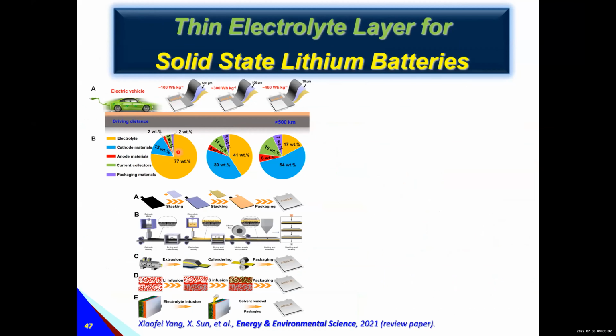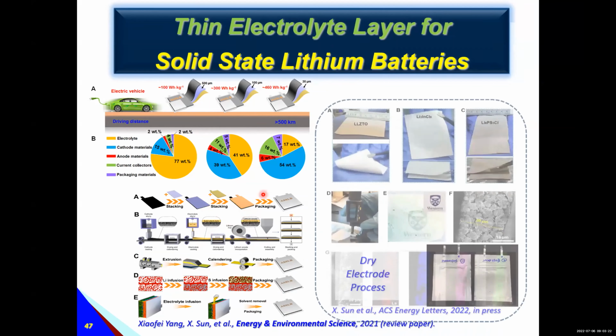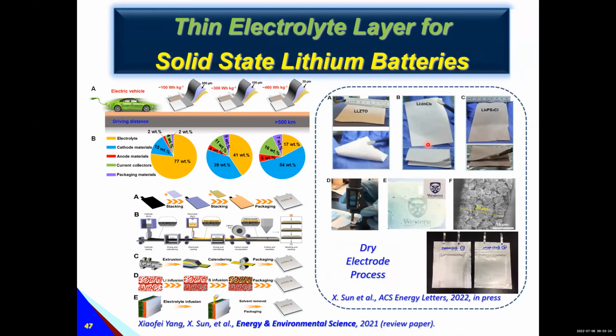Last part, I think not only the solid state electrolyte, we also need to work on the electrode. A very thin solid state electrode is very important for high energy density. So we have a summary. You can use different approaches to make a very thin membrane, down to about 20 micrometers. In this way, you can increase the energy density of the solid state battery. We demonstrated a pouch cell.